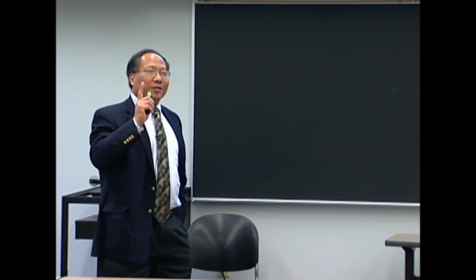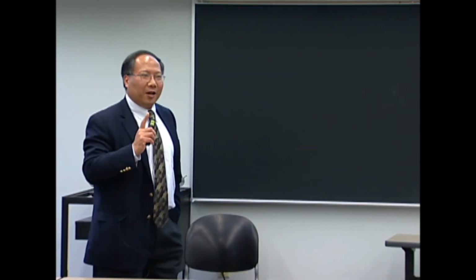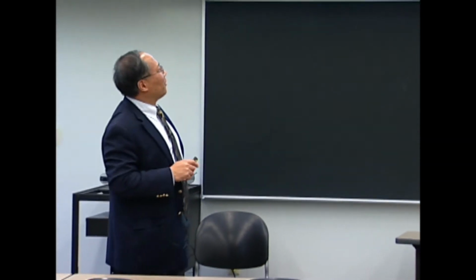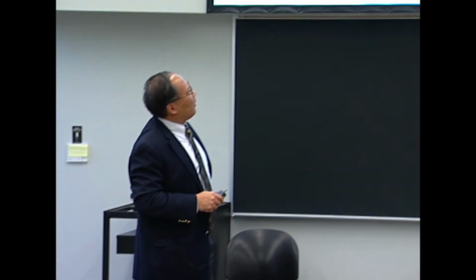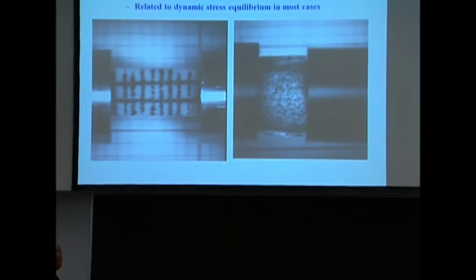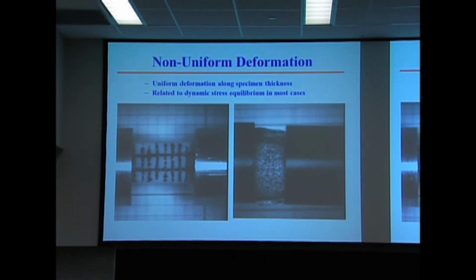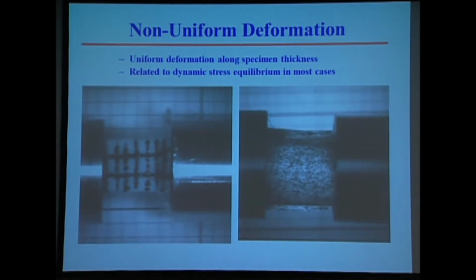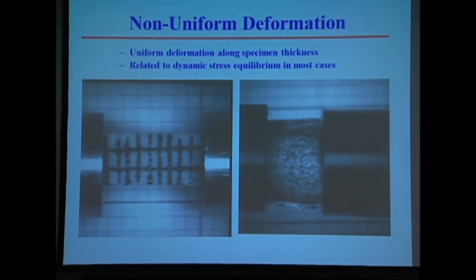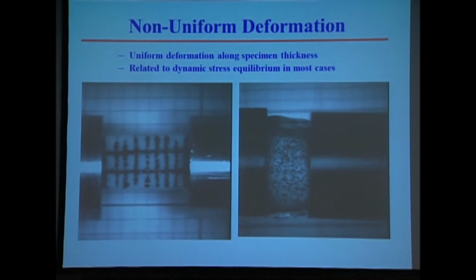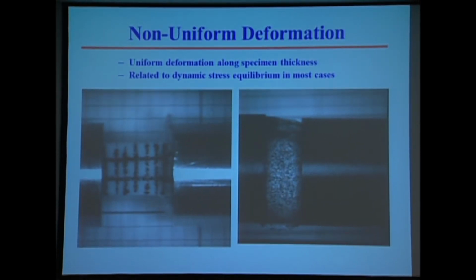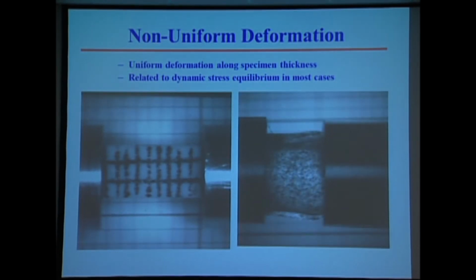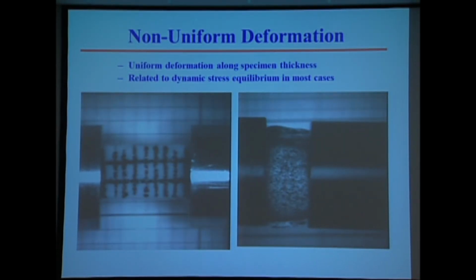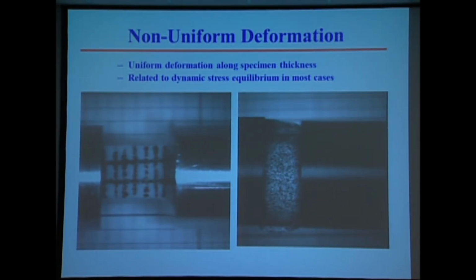So I'm measuring stress strain curves. The stress may be wrong if your sample is not as hard. And if you look at strain, if a sample is soft, do I talk about strain here or here? They're quite different. So for soft materials, if we don't pay enough attention to what we're doing, you mess up the load measurement, mess up the deformation measurement. You don't get anything valid.